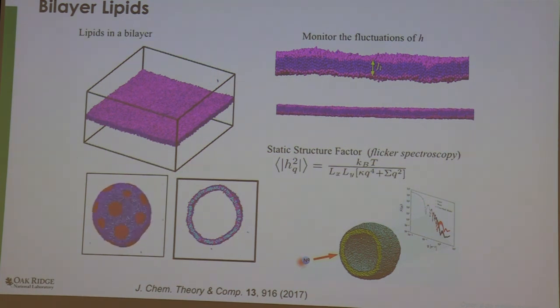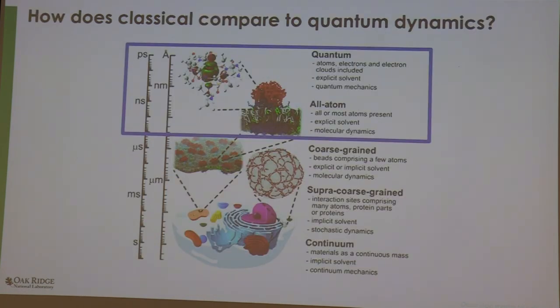Simulations actually show that quite nicely, that you form these beautiful domains, and these domains do penetrate through just like I showed you with the prior case. We were able to do deuteration, as I mentioned, and confirm that from neutron scattering. So that's sort of it for the classical simulations.